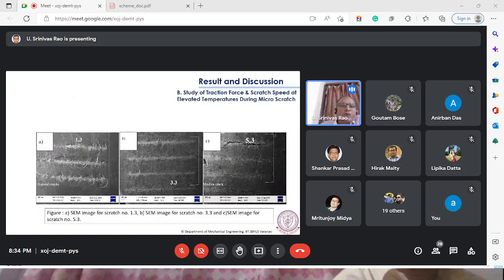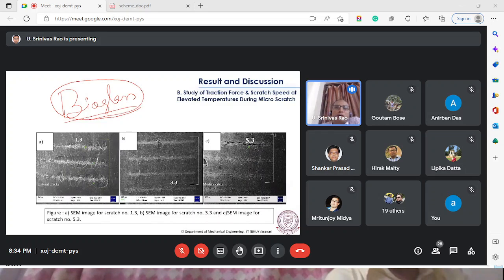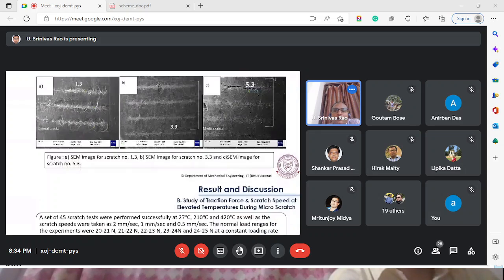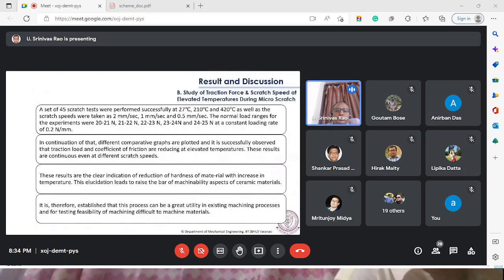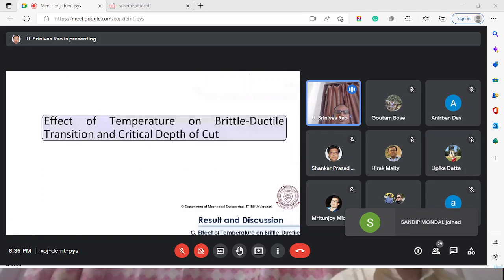And also the SEM images. Here actually there is some limitation in obtaining the SEM images. The specimen is bioglass, so there is a problem with looking at that through optical method or SEM. In both cases, taking images is difficult. So we need to have some coating, and then we can see the lateral cracks. So through all these, we can arrive at this: at different loads, at different temperatures, and different scratch speeds, we conducted the experiments.